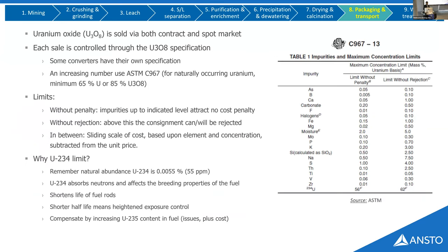So your product, you're looking at actually getting it out to customers. It's sold, as I mentioned before, on contract and spot markets. On the right there, you'll be able to see the ASTM method, that's actually given a reference in terms of what the specs have to be. You're looking at about, you know, minimum 65% U or 85% U3O8. There's two scales normally presented there, without penalty and without rejection. And there's a sliding scale in between.